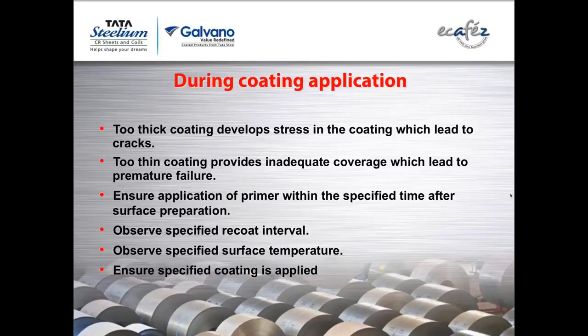Is 3-in-1 cleaning a recommended method for pre-cleaning or not, please suggest. Okay, nice question, very important question. None of the specifications, not SSPC, not NES, not ISO, mention this 3-in-1 process anywhere. 3-in-1 should be done on something which cannot be dipped into the chemical tanks, being very big in size, or which cannot be blasted. Up to say 1.5, 1.6 mm thickness, blasting becomes very difficult. There can be warpage of the material. Usually we say that above a thickness of 2.5 mm, blasting can be done, 100%.